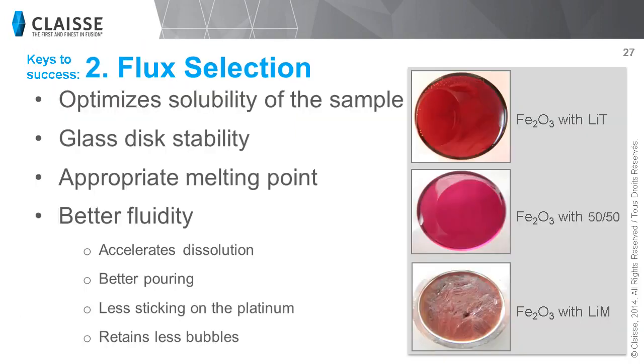This example illustrates the importance of choosing the right flux. In this slide, you can see a borate fusion made with iron oxide. In each of the three discs, we used the same amount of sample and the same method. The only thing that changed is the type of flux. In the first disc on the top, we made a fusion using only lithium tetraborate.